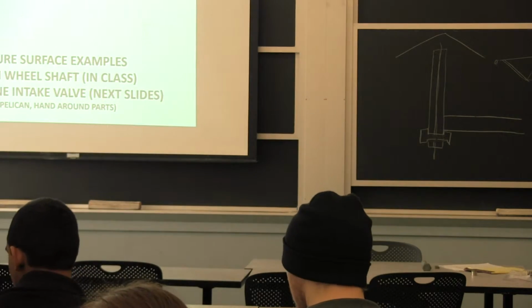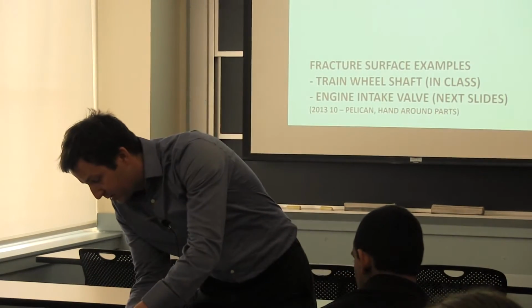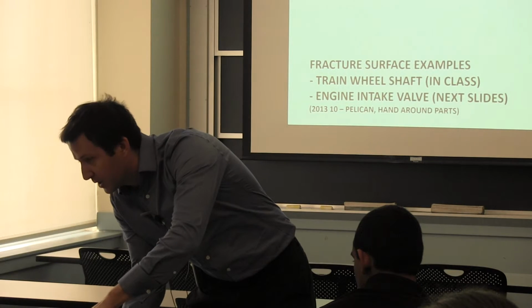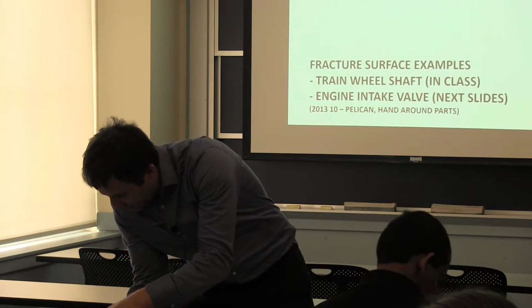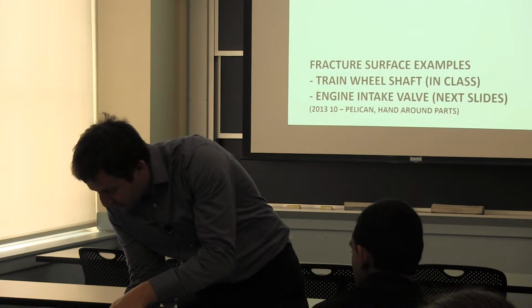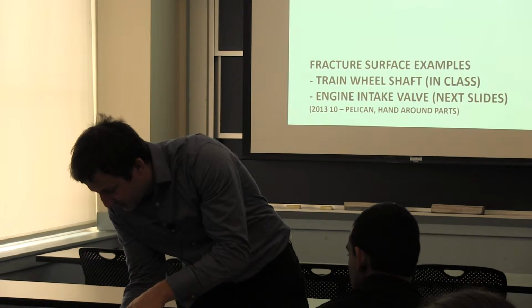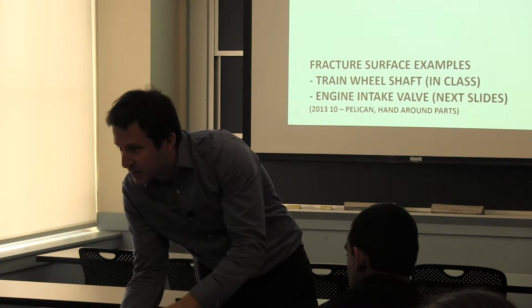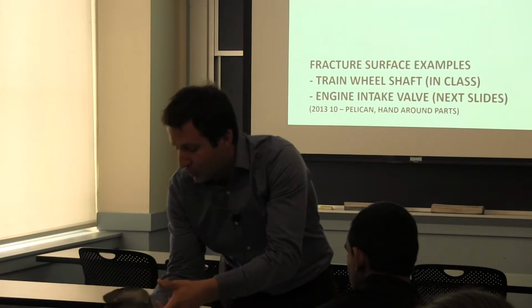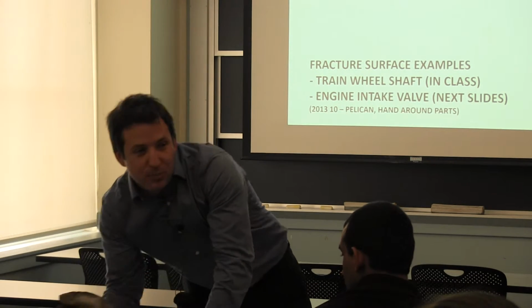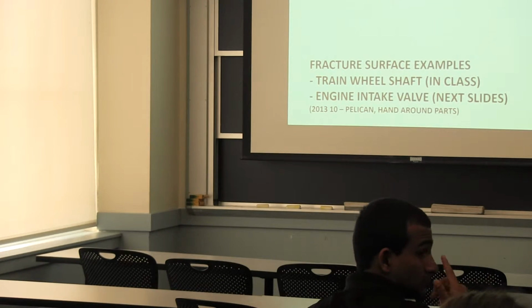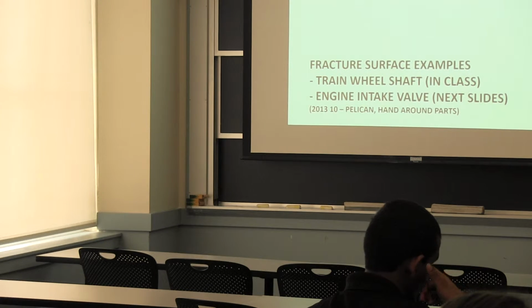Crack propagation line, this big step right here, tells me that over here the crack was going that way. And then the crack arrest lines are all these beach marks. So when I say beach marks, it's the same as the crack arrest line. It's where the crack was at a certain point in time. I'll put it somewhere. Just be careful. You guys are smart. There you go.